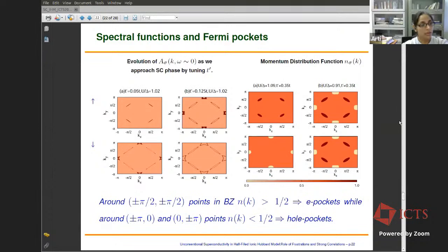And the same thing you can see if you increase the strength of the second neighbor hopping, because we know that we need a finite strength of the second neighbor hopping for the superconductivity to appear in this strongly correlated half-filled model. So if you increase the strength of the second neighbor hopping, keeping the ratio U by delta fixed, again you see that at very small second neighbor hopping, the system has very small Fermi pockets, and these Fermi pockets become bigger as you increase the strength of the second neighbor hopping, and that's the point where we start seeing the superconductivity. And this is just the momentum distribution function consistent with the spectral functions, which shows that at the pi 1 and pi 2 points you have the electron pockets, and at pi 0 points you have the Fermi pockets.